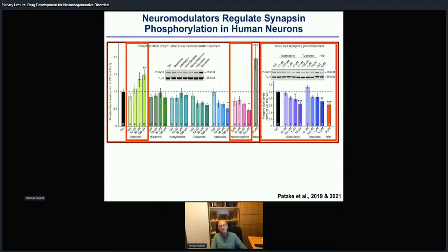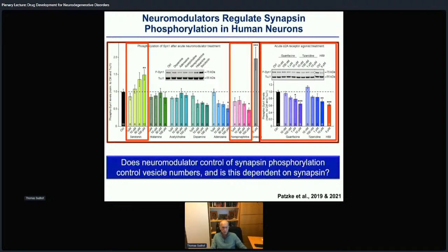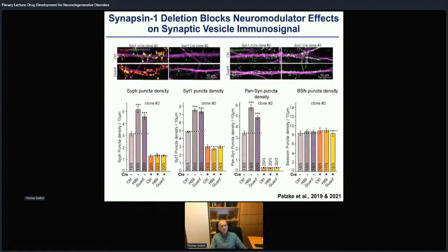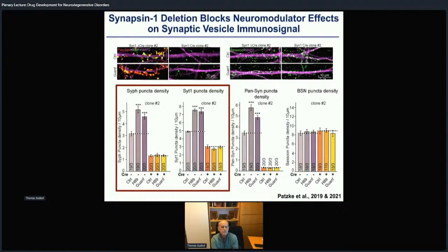And this then gives us a tool to check whether these neuromodulators will physiologically actually control synapsin phosphorylation dependent vesicle numbers. Okay, and to do this, we looked at this again. Now you see here an analysis of the synaptic vesicles using immunocytochemistry by measuring synaptophysin density and synaptotagmin density. And you can see that when you decrease the phosphorylation of synapsin with these agents, you actually increase the puncta number, suggesting, yes, you do have the same regulation by neuromodulators.